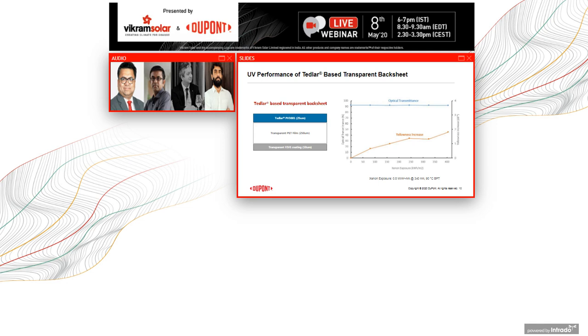So what we see here is the optical transmittance, which was at about 93, 94%, is very flat across all these hours. The other interesting thing is, as polymers are exposed to UV, the yellowness in the polymers can go up. In this case, it does go up a little bit. However, compared to any degradation in field performance, this is a very low increase, and it absolutely does not affect the performance in this case.